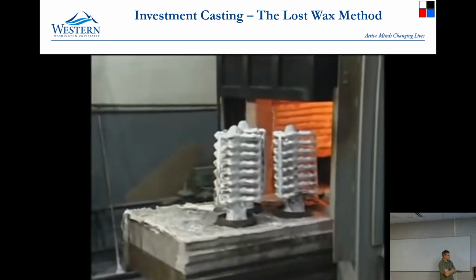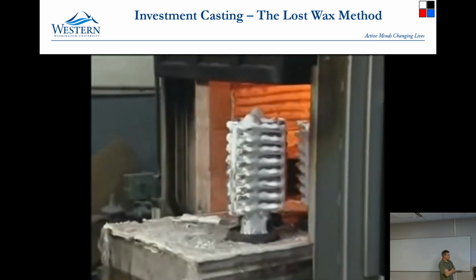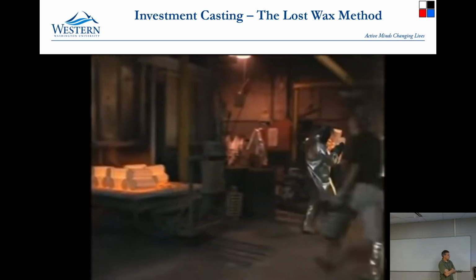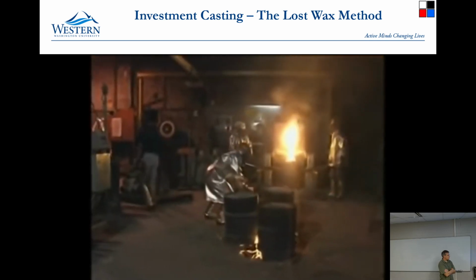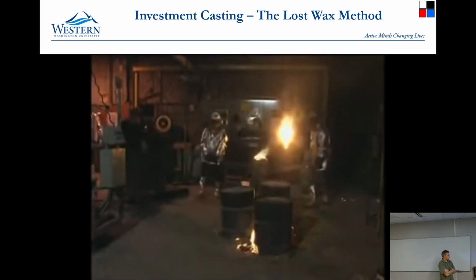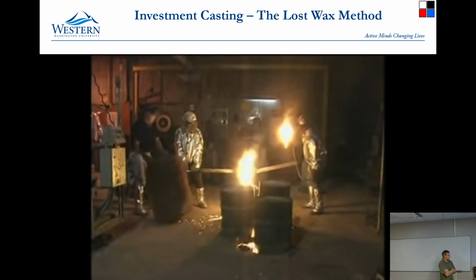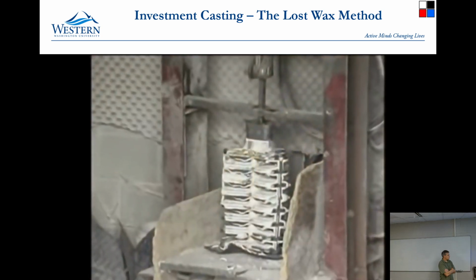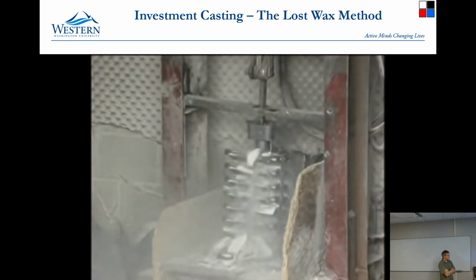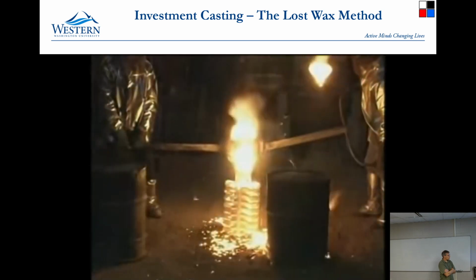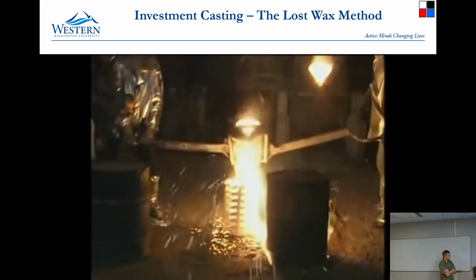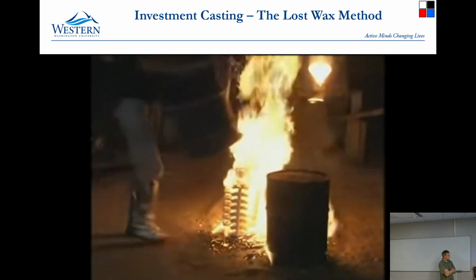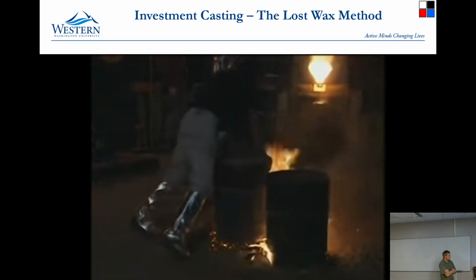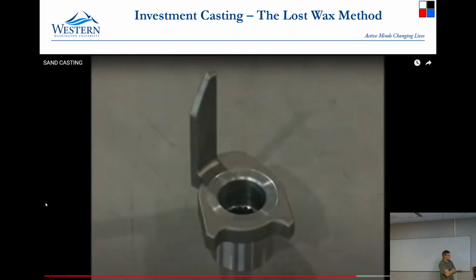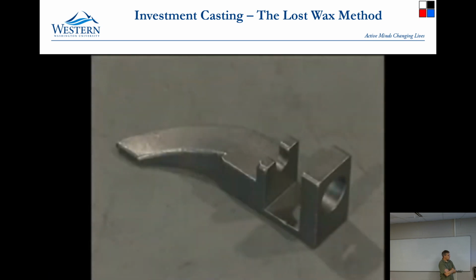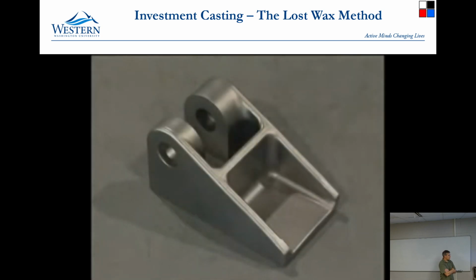The wax is removed from the mold by melt-out in a furnace or autoclave. Then the mold is fired to remove moisture, cure the ceramic, and to preheat it for pouring. Both ferrous and non-ferrous metals can be investment cast. Once the metal has solidified, the mold is broken and the casting removed. The main advantage of investment casting is the complexity of shapes that can be cast to close tolerances, thin walls, and smooth finishes. Most investment cast parts weigh less than 4.5 kilograms. However, parts weighing over 100 kilograms are also made.